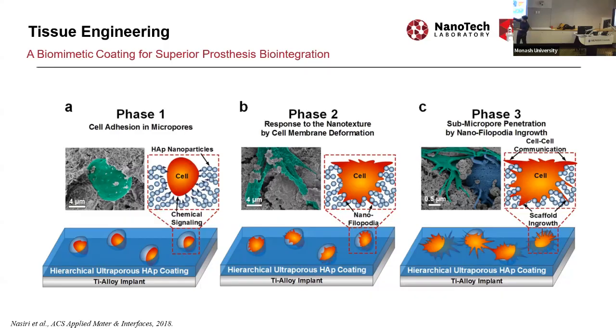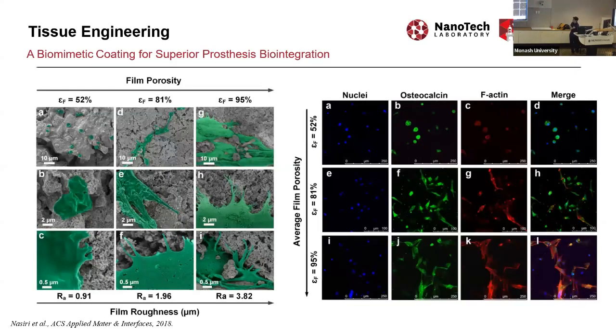When the cells sit on the surface, they start developing all these filopodia, and then they can actually communicate at the nanoscale with the surface, and they can bond, they can grow, and they reach out to each other, not only from the surface but also from the very deep layer into the film. And that creates a significantly high adhesion of the cell to the surface.